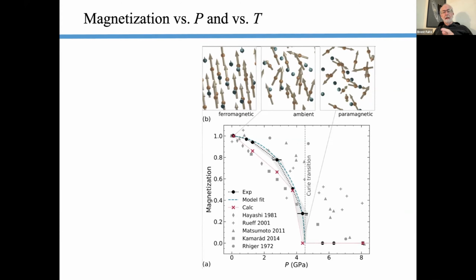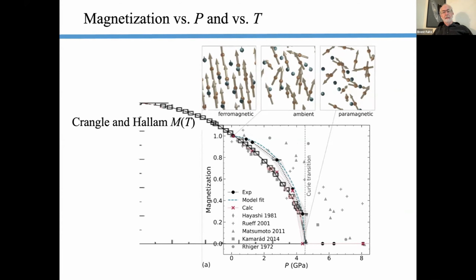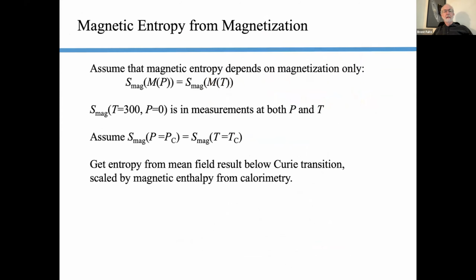As I said, it's not a 0 disorder at room temperature. And if we overlay it with the magnetization as a function of temperature, aligning it up at the Curie point, we get this. And here's our room temperature behavior, which is in both of the curves. And it might be that there's a little bit more of a curvature for the pressure dependence of the magnetization than there is in the temperature dependence, but I don't think very much.